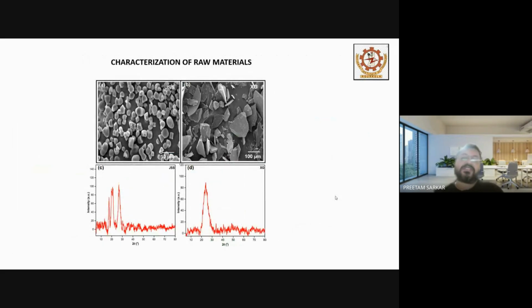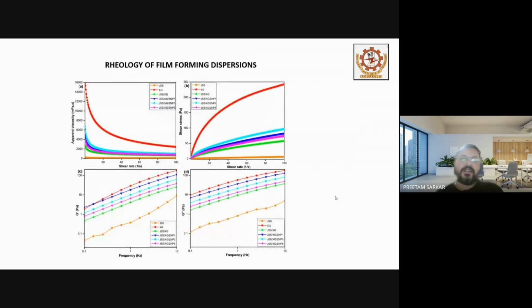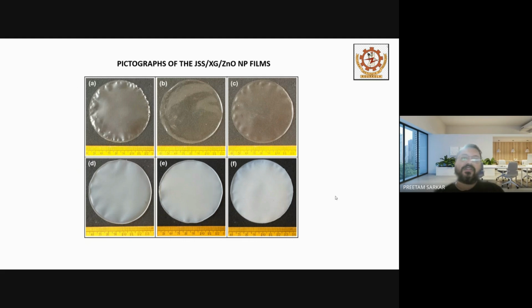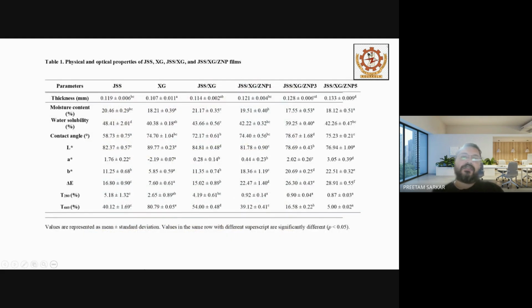These are again our characterization of the raw materials, our jackfruit seed starch and the tamarind kernel xyloglucans, FESEM data, and our XRD data. Then we have the rheology of the dispersions, and then we prepare these films, starting off from the control films. Because zinc oxide itself is white, as you increase the zinc oxide nanoparticle concentration, the whiteness index of the film also increases. These are our different parameters like thickness, moisture content, water solubility, and contact angle. As you can see, contact angle increases from 58 degrees to 75 degrees, a significant increase.